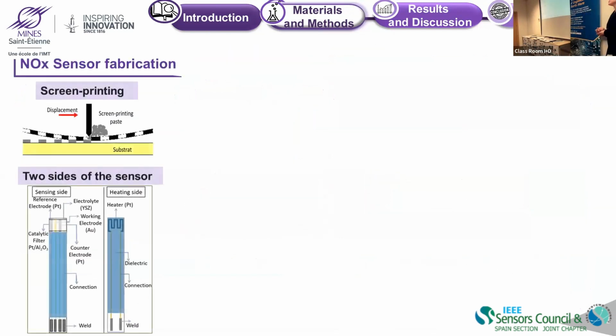Regarding the NOx sensor fabrication, it is totally prepared by screen printing. So we start with an alumina plate, and we deposit all the elements by screen printing. On one side, we will have the sensing side, with the YSZ electrolyte, the 3 electrodes, and the catalytic filter. On the other side, there is a heating element in order to get a self-supported sensor.